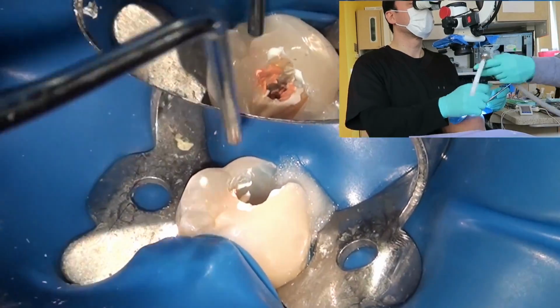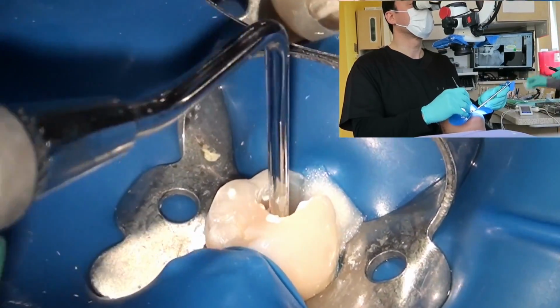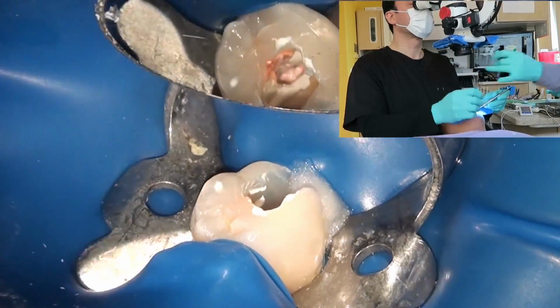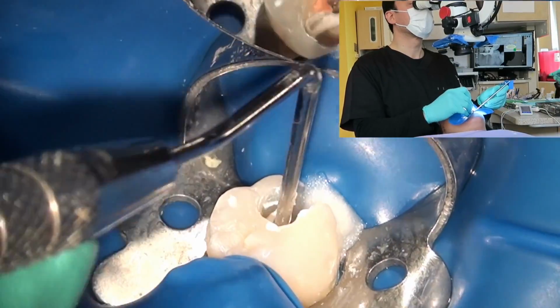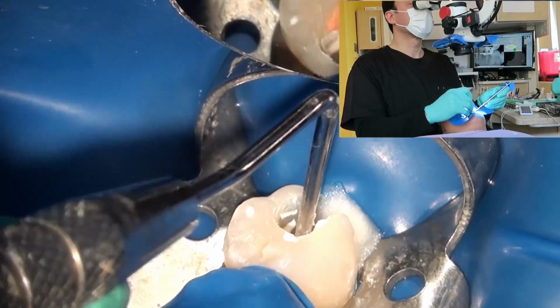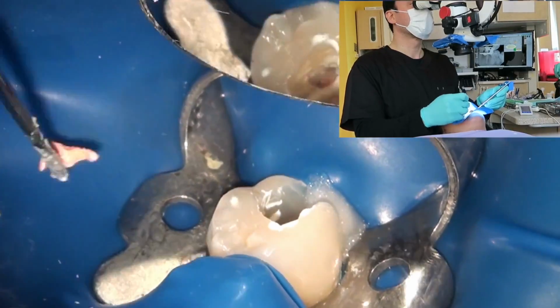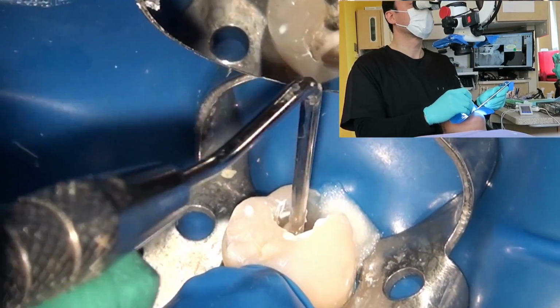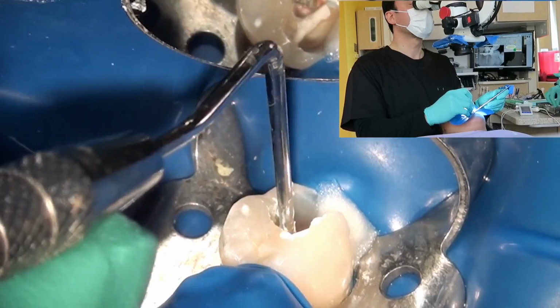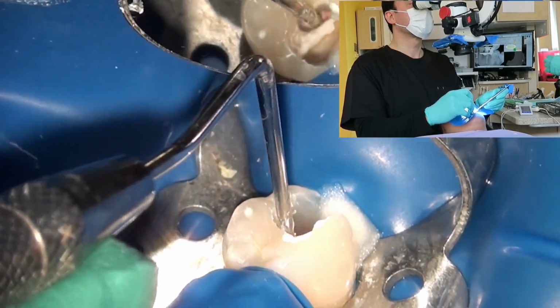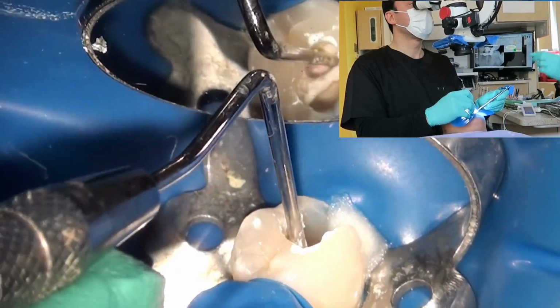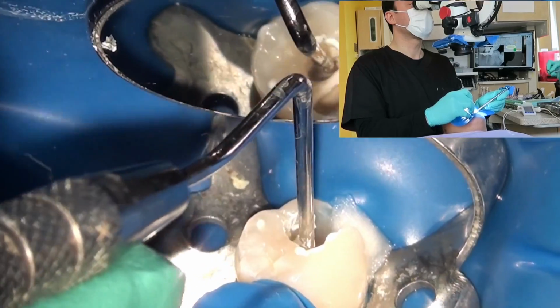forces. So using the Endo Pro 270 at high temperature, sear off right at the level of the orifice without having to go too far down, and then use the largest plugger, here's a size 10 first, and followed by a size 9, to take the molten gutta percha and spread it everywhere, so that you end up with only gutta percha on the surface without showing any sealer interface.